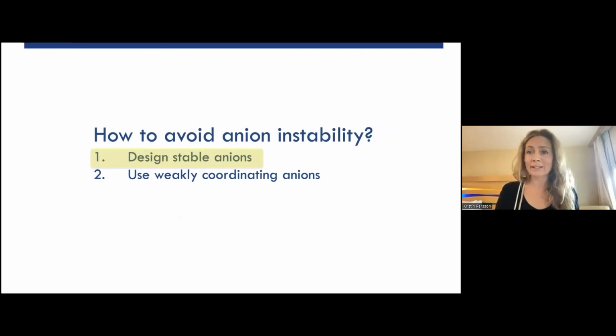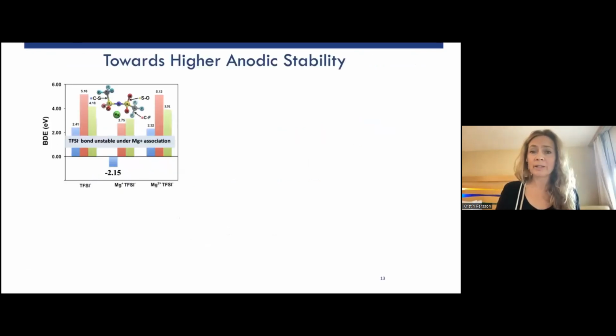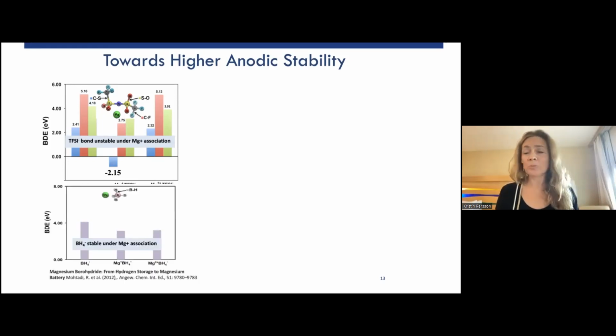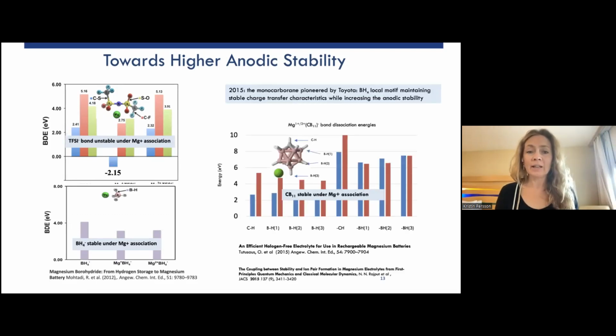So how do we go about designing from computations, or helping out with computations, more stable anions? Well, we think we understand the instability of TFSI, but of course you also have to corroborate it on things that are known to be quite stable. And borohydride is one of those. It has a low anodic stability of 2 volts, so it is not really viable for high energy density magnesium batteries, but it is known to work quite well with magnesium metal. And indeed, if we calculate not just borohydride by itself, but also coordinated with magnesium 2 plus, as well as magnesium 1 plus, this highly reactive cation, it is still stable. This bond doesn't break. So again, we're starting to feel a bit better about our hypothesis. And carrying that motif forward in 2015, Toyota also proposed a monocarborane, which has the same borohydride motif.